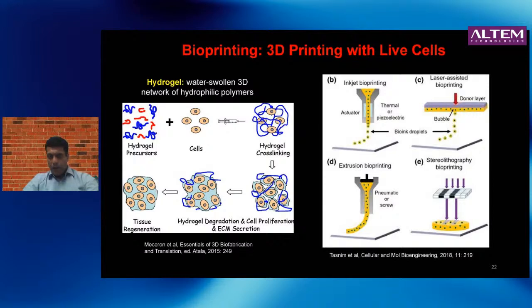But what is by far the most popular way of doing 3D printing is extrusion-based bioprinting, where you have a printer head, typically some sort of pneumatic or screw system, where you take the gel with the cells and you push at the one end so that through the nozzle the gel will come out, and it will get laid down layer by layer, and you can build up a cell-seeded scaffold as your 3D printed part.